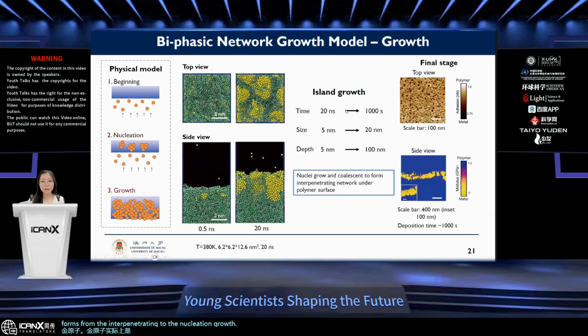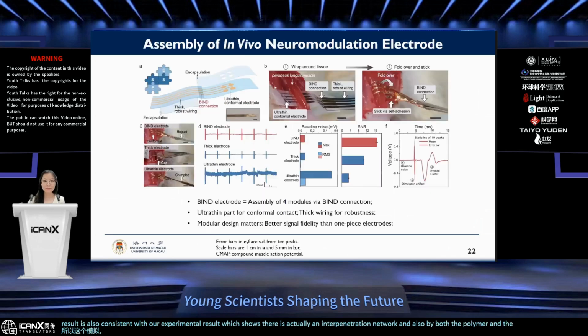nucleation growth. And then after the first few tens of nanoseconds to an experimental time of hundreds or 1,000 seconds, the nucleation grows, and then the nucleations of the micro nanoparticles contact each other and merge, and then make a continuous conductive pathway. So this simulation result is also consistent with our experimental result, which shows there is actually an interpenetration network, and also both the polymer and the metal nanoparticle are continuous.